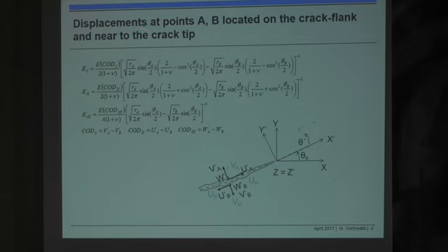So what we have here is a crack opening displacement in the mode 1 and in the mode 2, and also, which is new now, in the mode 3 direction. And if you have seen the specimen itself, you see that there is obviously also in our experiments mode 3 contribution present. So we took the Williams series and resolved them with respect to K, and the input are these crack opening displacements in mode 1 and mode 2 and mode 3.